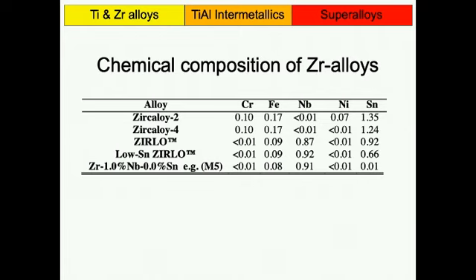And then you have Framatome, which has gone much more extreme in a way. They've just got rid of the tin and have the niobium content. They have some problems with the alloy. It doesn't seem to be a very robust alloy. Every now and then they seem to have a problem with it. I've seen that they're also now looking again at alloys where they add a little bit of tin to it. But why this alloy is less robust than this, maybe, it's completely unclear. There's so many unknowns still in this sector, it's quite unbelievable.